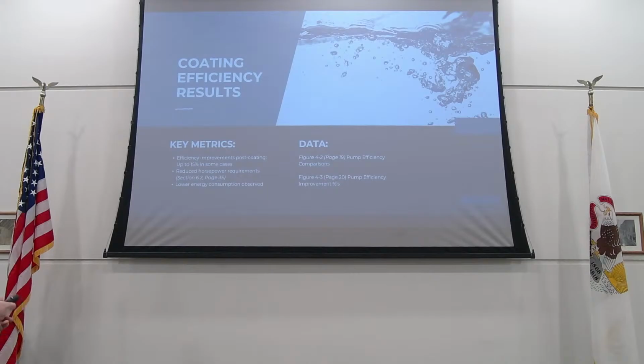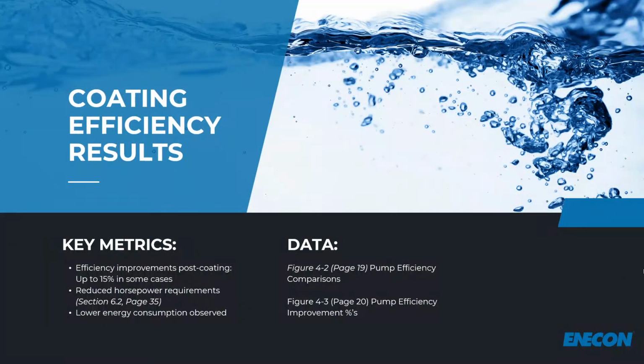So here's the key metrics. The efficiency results of the study: efficiency improvement post-coating was up to 15% in some cases. It all depended, and it also depends on your runtime, right? If you're running 24/7 versus running 4 hours a day, 8 hours a day, whatever it might be here. So I'll get into this.